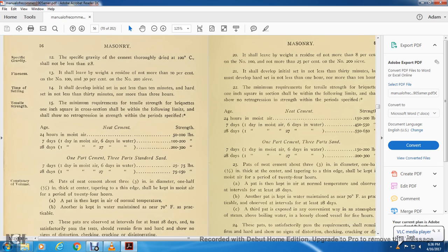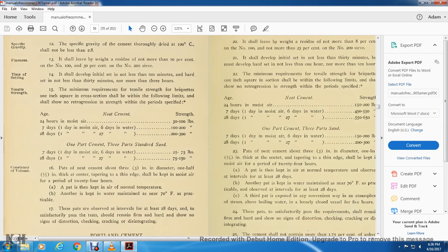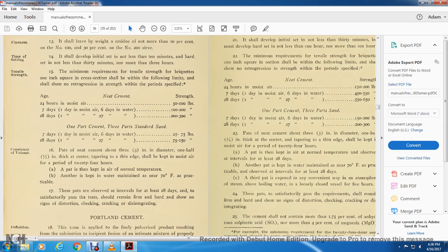1 part cement to 3 parts standard sand. 7 days, 1 day in moist air, 6 days in water, 25 to 75 pounds. 28 days, 1 day in moist air, 27 days in water, 75 to 150 pounds.